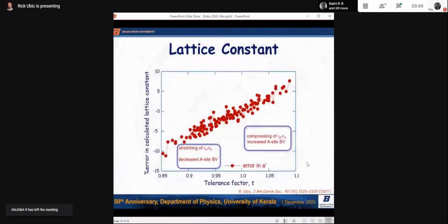All right, so let's look at our modeling. If we use A prime to calculate the lattice constant, then we get a curve like this. There are 132 data points along this curve. And this is the percent error in the calculated lattice constant. Right? So if A prime were perfect at calculating the lattice constant, we'd get a line at zero error, right? But we don't. We get this positive sloped line, basically, right?